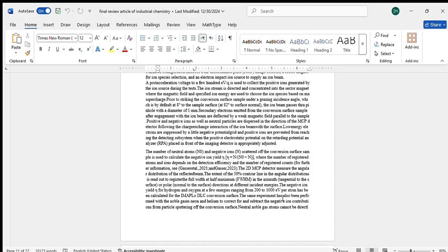The extent of the 50% contour line is the angular distribution, read out to the registrator, full width at half maximum in the azimuthal or the polar directions at different incident energies. The negative ion yield for hydrogen and oxygen at a few energies ranging from 200 to 1000 electron volt per atom has to be calculated for the IMAP-Lo DLC conversion surface.